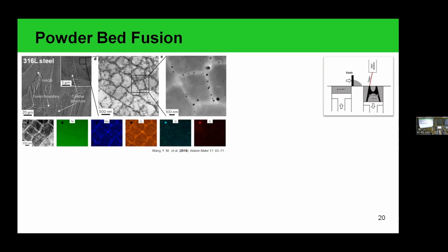smaller structural objects. So here you can see austenitic stainless steel, which consists of a cellular structure as the substructure, and we see that these cells are surrounded by dislocations. Also, we see that these cells do not have a homogeneous element distribution. And we also observed small precipitates like oxides at these cell boundaries.